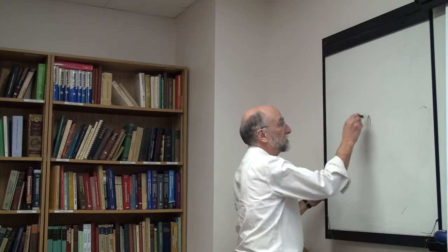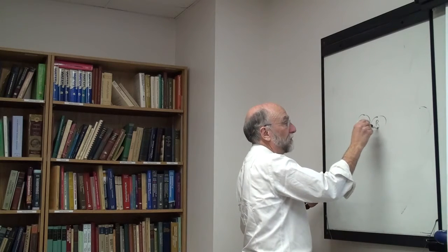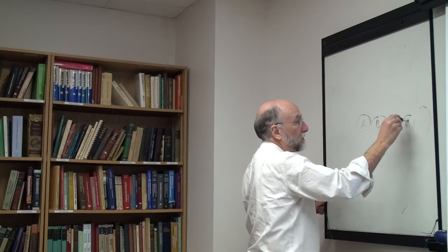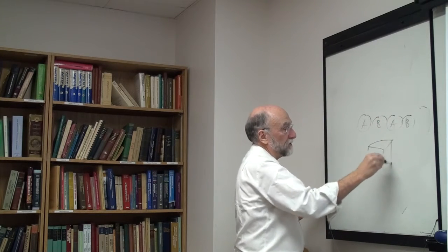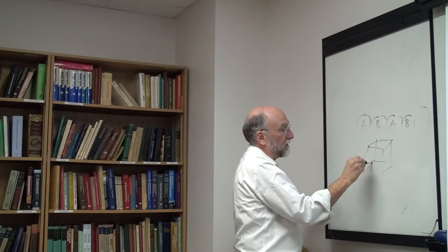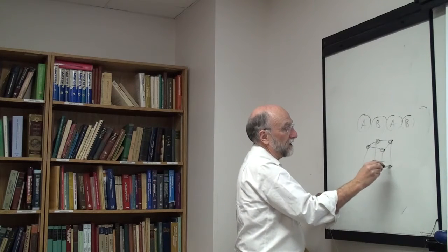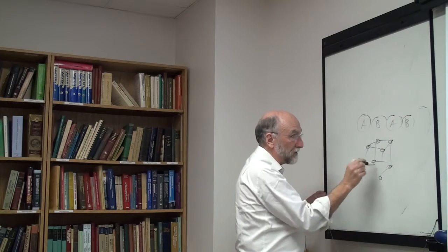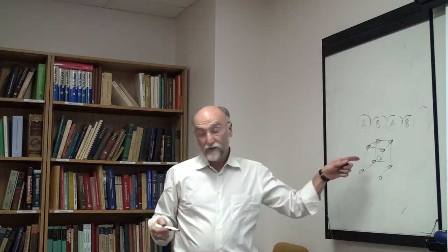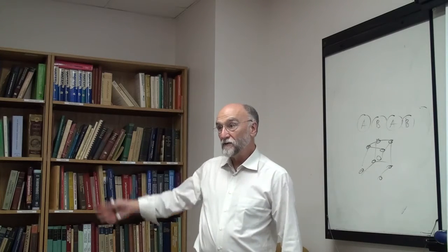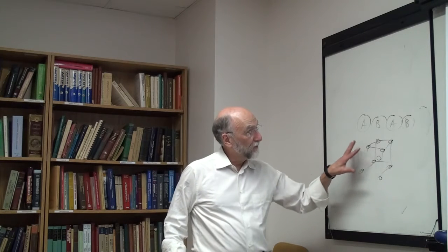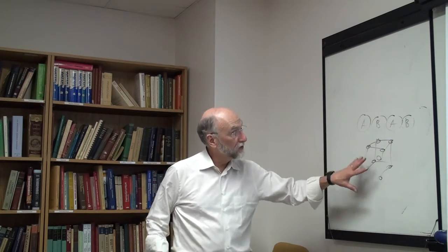Now, in long-range order, you basically have 2 sublattices. You have a sublattice for A, and you have another sublattice for B. For example, in the cesium chloride structure, you have the cesium chloride unit cell, with cesiums on the corners, and that's one sublattice. And then in the center of the cell you have your chlorine, which is the other sublattice. And these are distinct sublattices going on for huge numbers of atomic distances. So this is quite distinct from short-range order. This is long-range ordering.